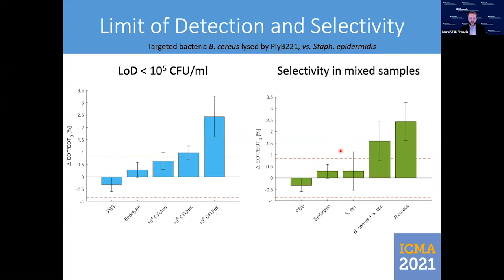Here we did several tests with also another bacteria, the Staphylococcus epidermidis. And when we have a mix of both, we can see clearly that we do not detect the Staphylococcus, which is not lysed. And we have a clear detection in the case of the mixed bacteria solution, where we have, of course, the detection of the Bacillus cereus.